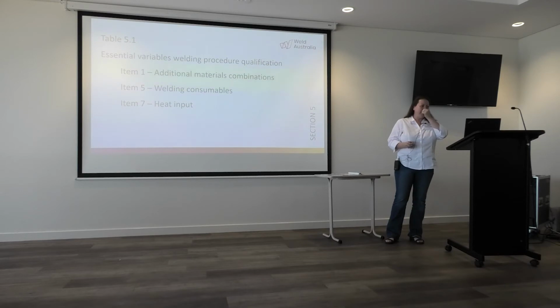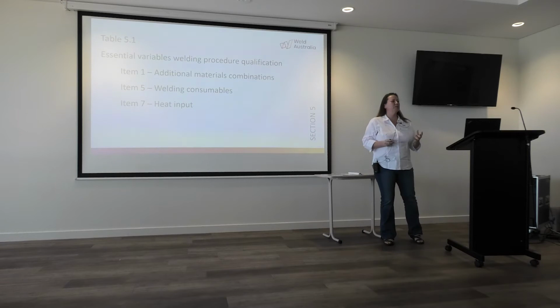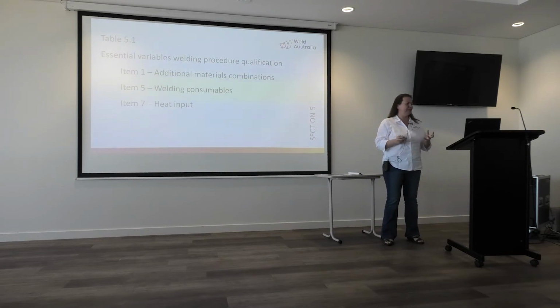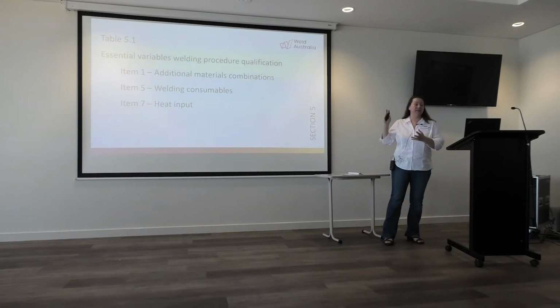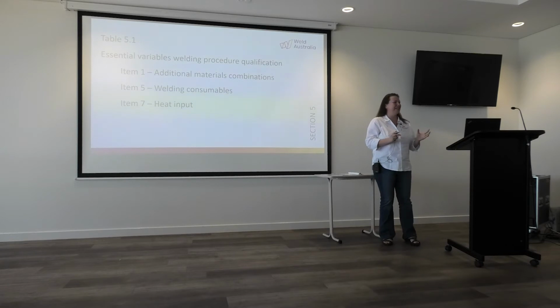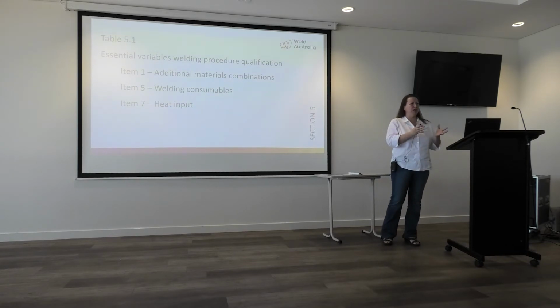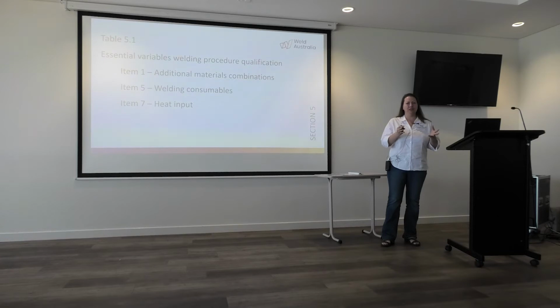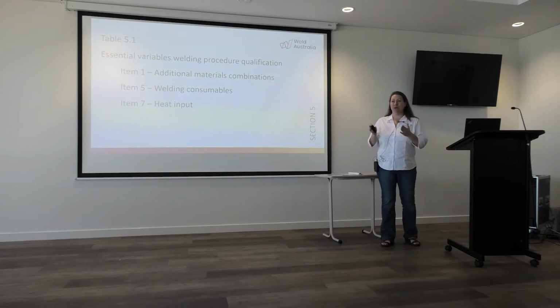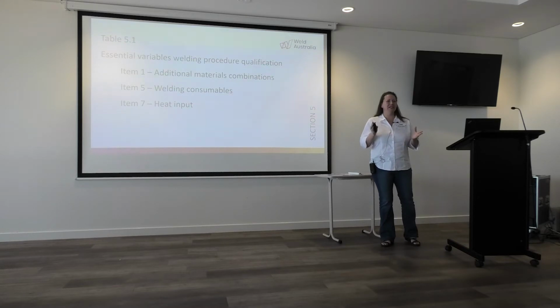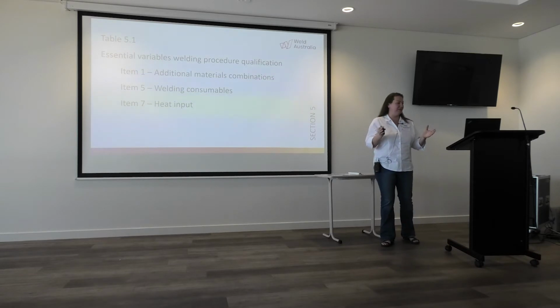So table 5.1, under item 1, additional material combinations were now added, which we'll get to in the physical tables that show that. And item 5, welding consumables. This actually changed to say that if you don't use a welding consumable within the manufacturer's requirements or within the standard it is actually supplied to, that procedure is not qualified. So testing of a procedure doesn't justify using it outside the range that it was designed for.